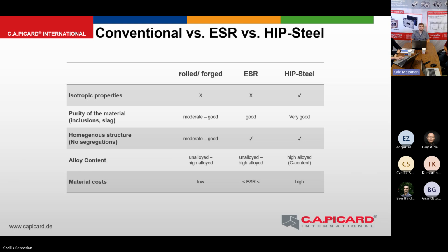Here I put a table where we compare rolled and forged steels to ESR steels and HIP steel. ESR means electro slag remelted. That means we remelt a steel and, like, filter it through the slag. Therefore, it gets better properties, but the HIP steels are the only steels with isotropic properties. That means that you don't have any direction properties, or not depending on the direction.